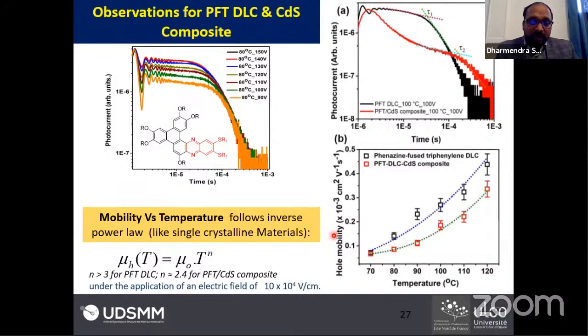So we went into the literature again and tried to discover what is happening. Then we found that if this discotic liquid crystal in one column is behaving like single crystal materials, then in single crystal materials the charge carrier mobility increases with temperature following a power law. So we fitted our charge carrier mobility versus temperature curve using this power law, and we found that yes, it follows this law. But N is greater than 3 for the PFT, and for the doped system, N is equal to 2.4.